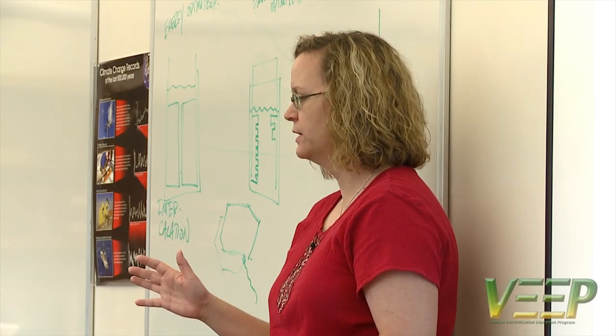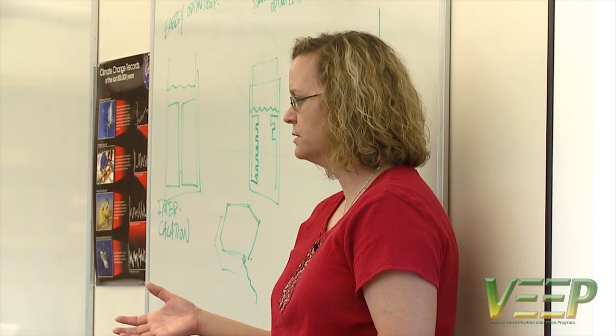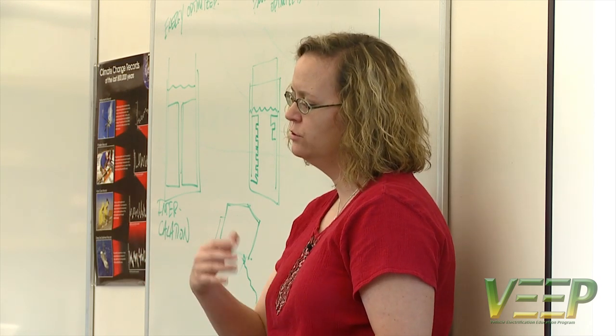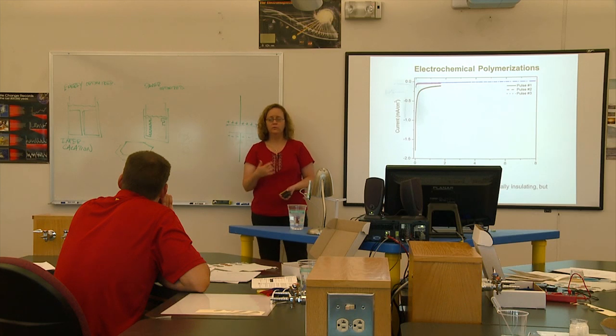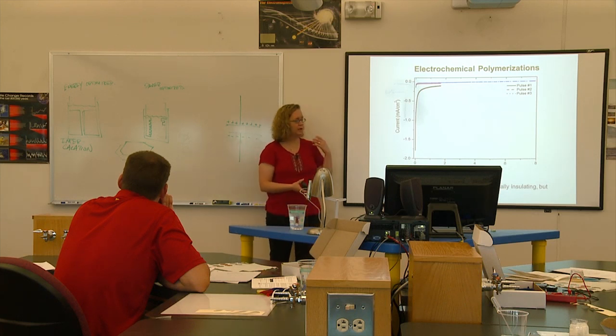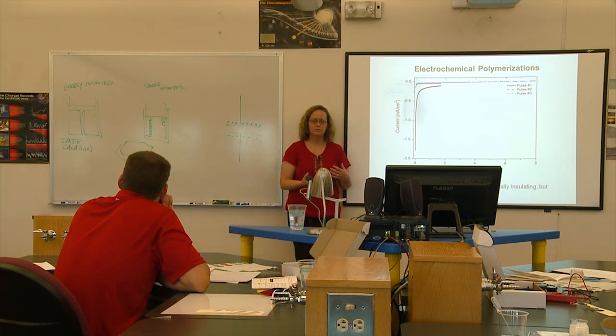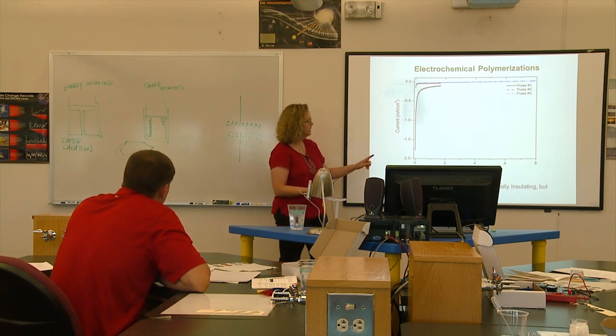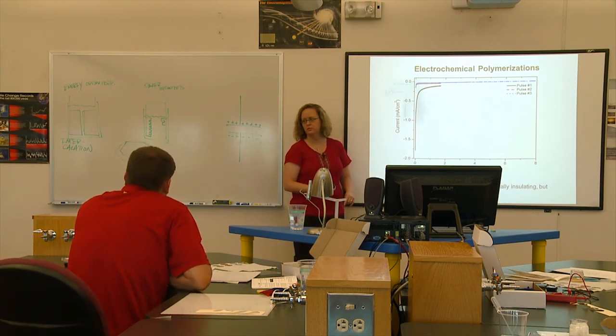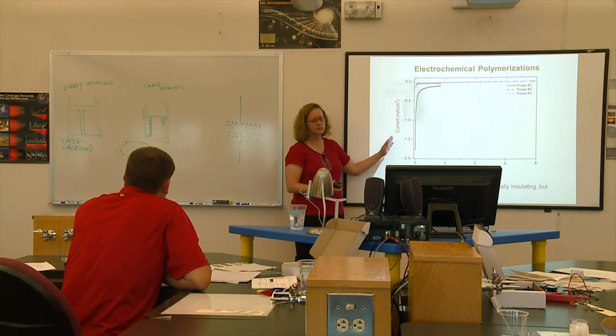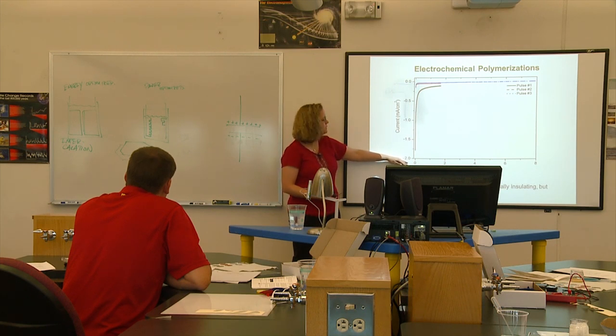If there are defects, and these are typically called pinhole defects, then when you add the cathode in, you'll get a short. So the way that we monitor this is we apply a voltage. These are polymer electrolytes that we've developed because there really isn't anything in industry that can be made this way that works the way we need it to. If you look at the black line, this is the first pulse. So we measure current as a function of time. And now this is zero, and we're going to negative current because we're doing a reduction.